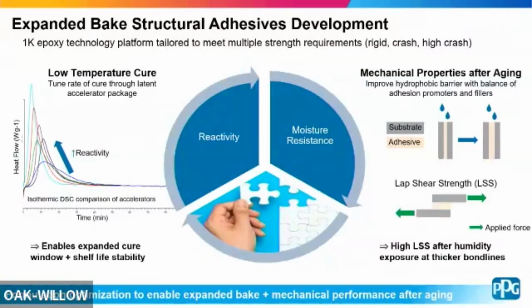And on top of that, if we're taking into account potentially needing thicker bond lines, especially for structural adhesives, we've seen from typical 0.2 millimeters closer to 1 millimeter. You can see my highly sophisticated graphic showing that as you increase the bond line, you're going to have more susceptibility to moisture. So you really want to make sure you're increasing your hydrophobic barrier, so you're getting more moisture resistance. You get the same mechanical performance after humidity or exposure.